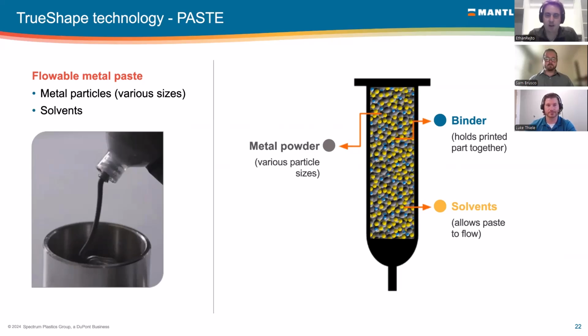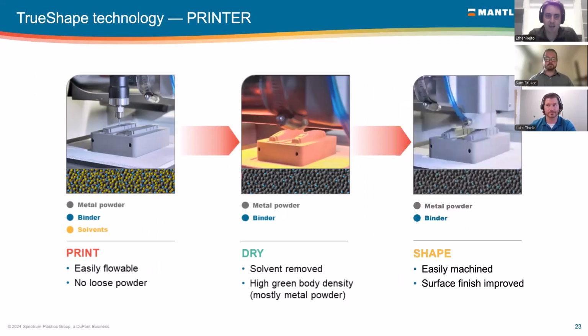The first step in processing this paste is to print it. We start by just extruding this material out of a nozzle. It's viscous enough that it can be easily extruded, layer by layer. It's very easy to flow, and of course there's no loose metal powder, because all of that metal powder is mixed in with the paste.